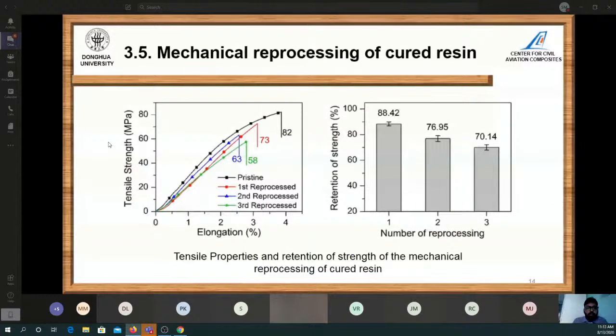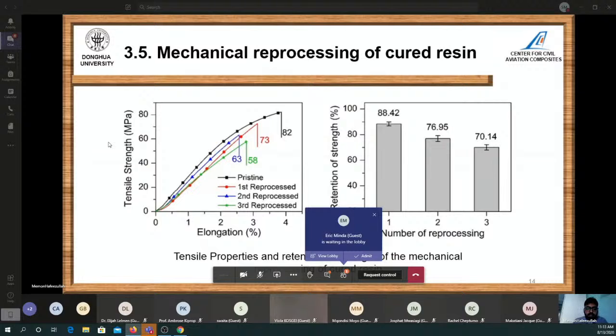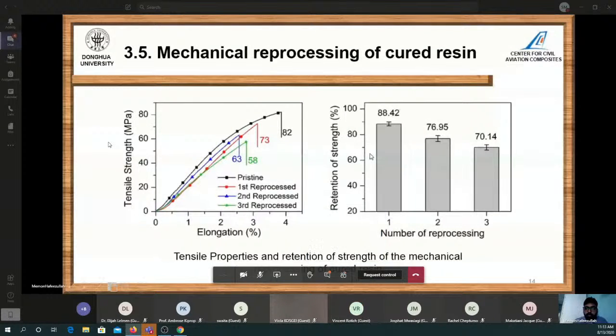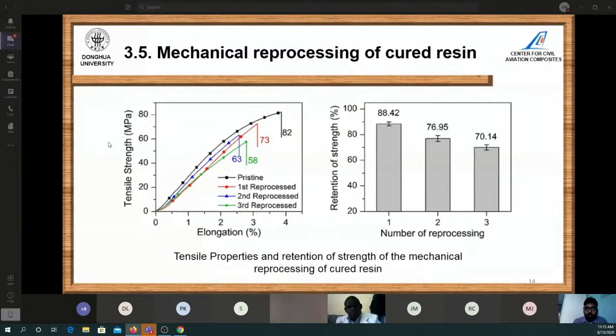So these were the mechanical properties, the mechanical reprocessing property of the cured resin, that for the pristine one, we could get 82 megapascal of strength, and in the first cycle, it decreased to 73, and it was further decreased in the second and third respectively. But overall, after the different number of reprocessing, we get enough high strength, like 88.42 self-healing efficiency, which was quite high, and 76.95 for the second cycle and third cycle.